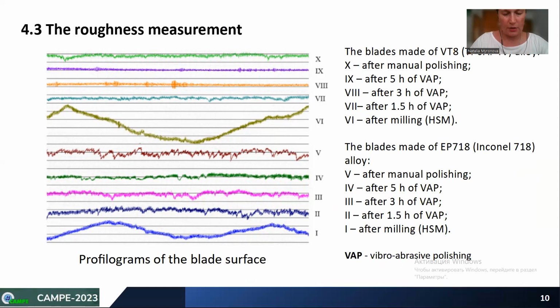The roughness measurement results for the blade profile surface before and after the finishing process are presented as a profile graph for the different machining options. Vibro-abrasive polishing takes from 3 to 5 hours to achieve the required roughness of 0.2 micrometers.